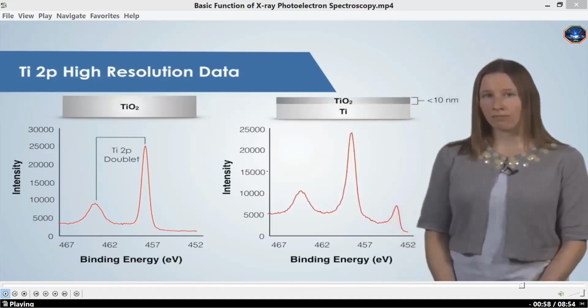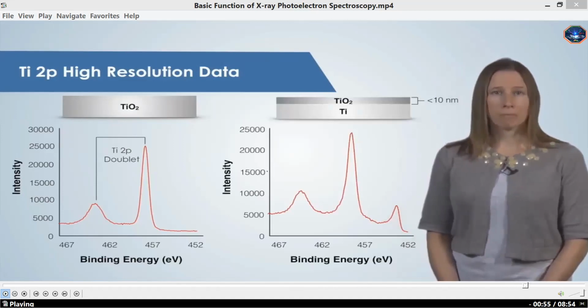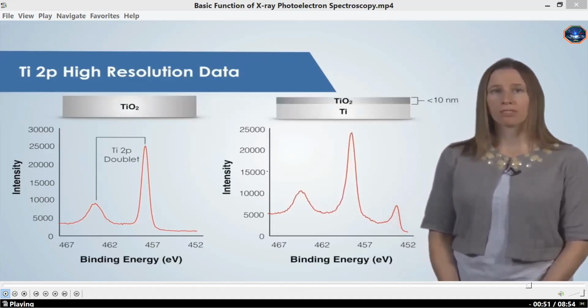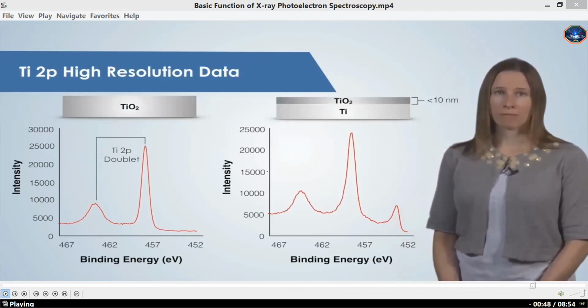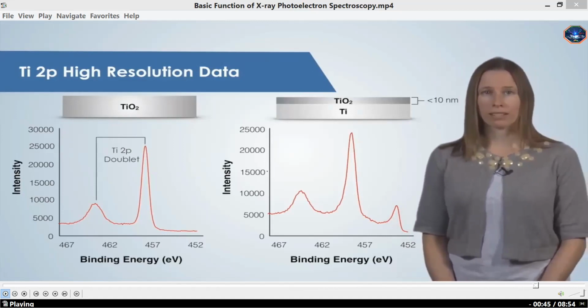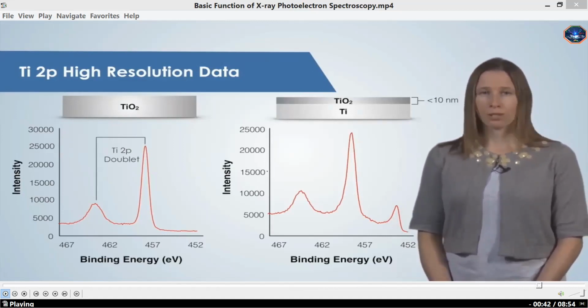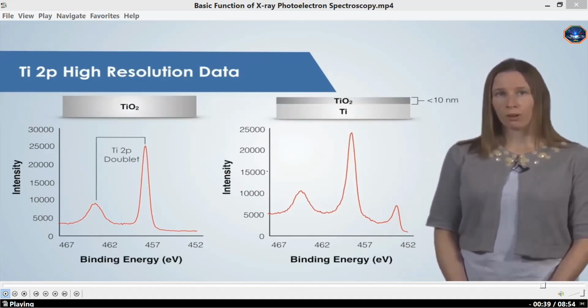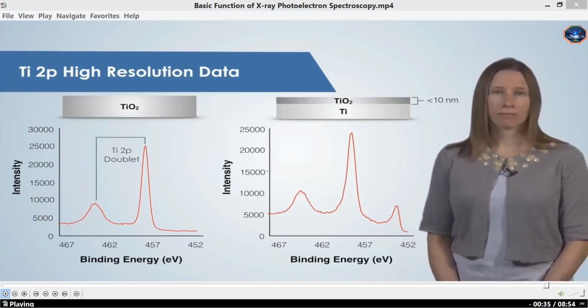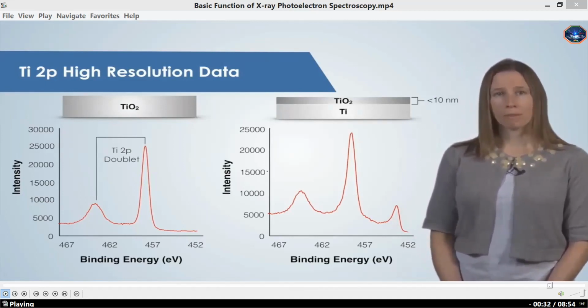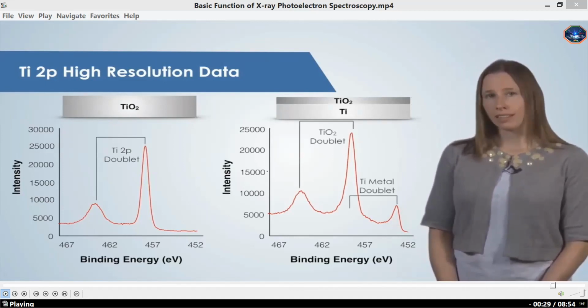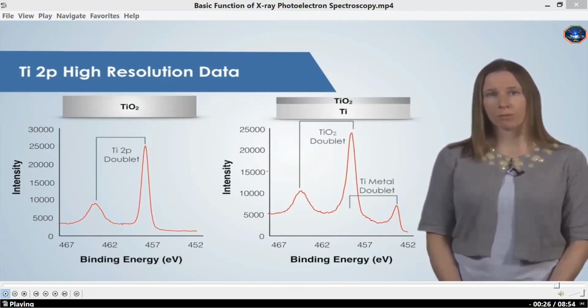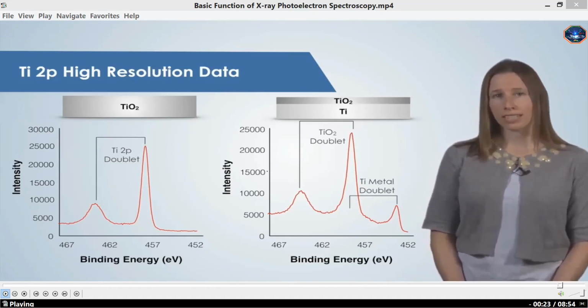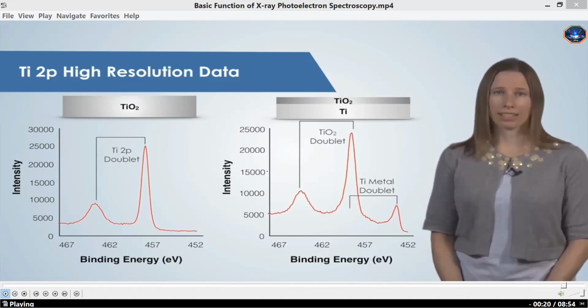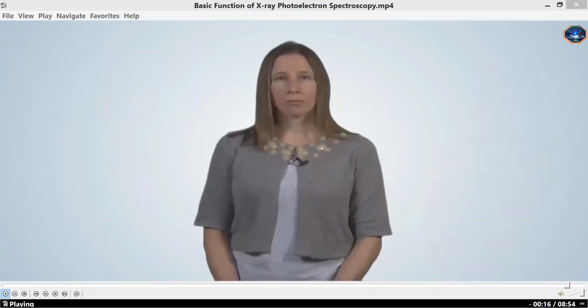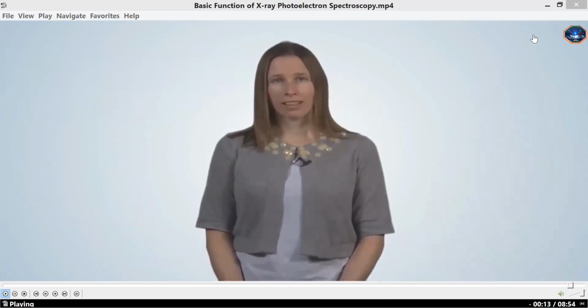But if we have a very thin film of TiO2 on top of titanium metal, we may be able to observe the signal from both the TiO2 and the titanium metal. Remember, the depth of analysis for XPS is only about 10 nanometers. So if the TiO2 is less than 10 nanometers thick, we may be able to see some signal from the metal below it. In this case, we observe another peak at a much lower binding energy. This extra peak is part of a second titanium 2p doublet that partially overlaps with the TiO2 doublet and is due to elemental titanium. I hope this video helped you to understand that analysis by XPS can provide a lot of useful information about the surface of a sample.